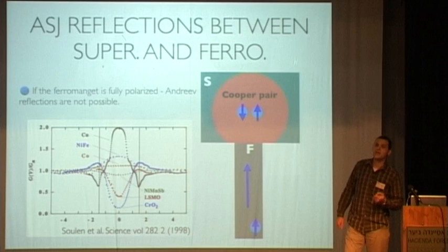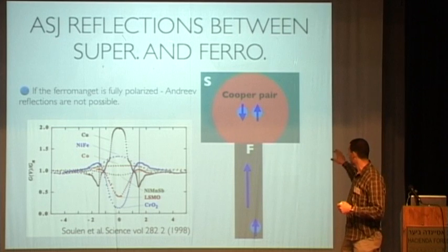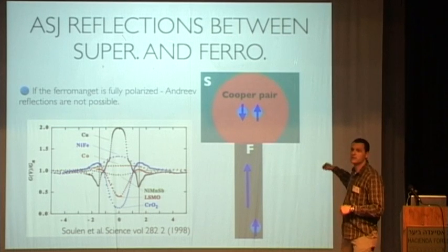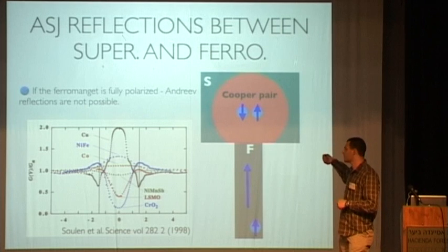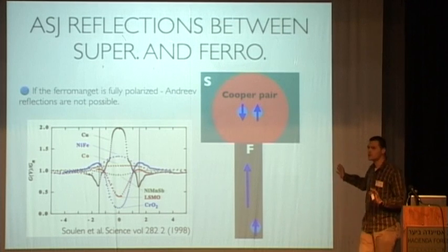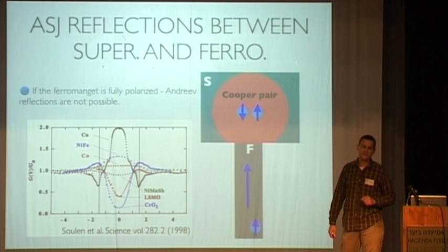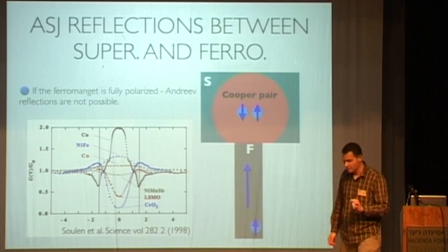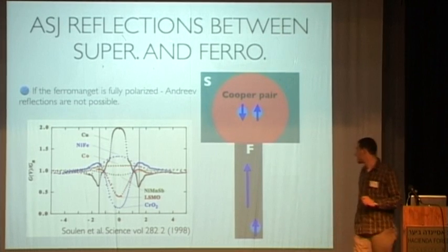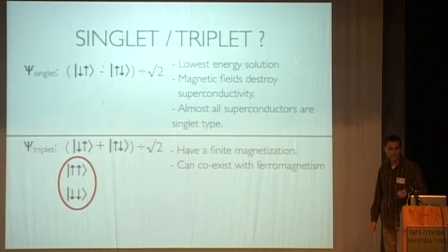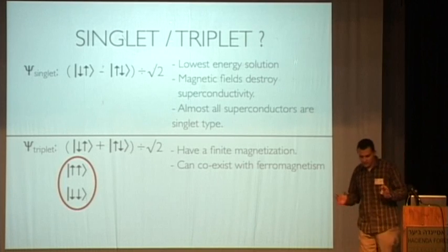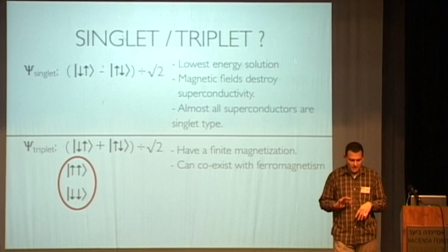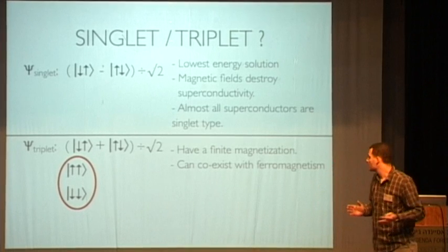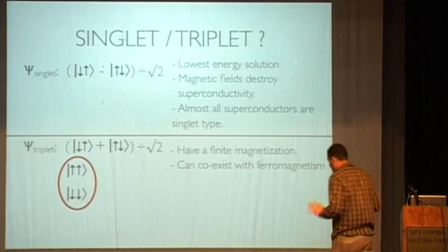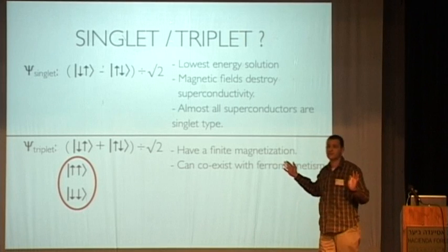And we would not see an enhancement in the conductivity of the junction, the conductivity of electrons entering the superconductor. And this effect was used to measure the polarization of various ferromagnets in this very nice experiment by Soulen. Now, I mentioned spin opposite electrons, equal spins. It basically goes down to the question of singlet triplet for physicists.